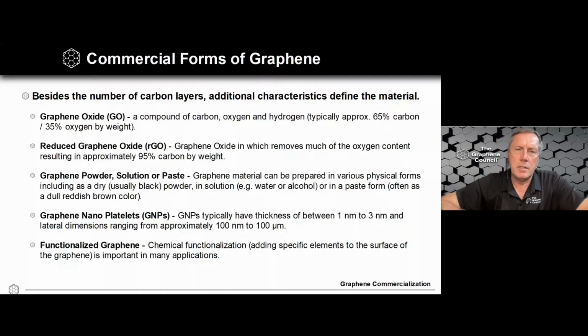And besides the layer count on defining graphene, you also have different forms or types of this material, so that in essence, graphene should not be thought of as a single material, but more like a family of material. And within that family, you have things like graphene oxide, which typically has about 35% oxygen by weight. You can also create graphene oxide and then reduce the oxygen out of it so that you're left with about 5% oxygen. And that gives you a reduced graphene oxide. And both of those materials behave in unique and special ways.